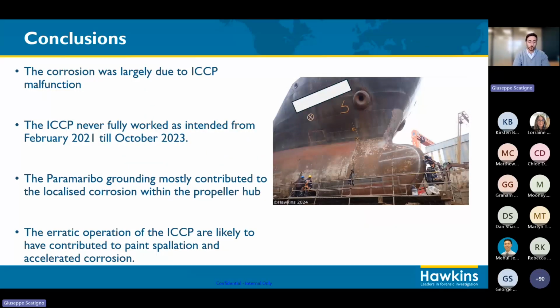I was also able to apportion the damage that the propeller hub had seen to the grounding, and therefore I was able to help the insurer in apportioning the claim that the vessel owner had brought forward, and effectively in minimizing the event of the grounding itself, which yes did possibly strip some of the coating, but effectively did not erode the majority of the hull, and all of that had been done afterwards by the lack of appropriate current protection.